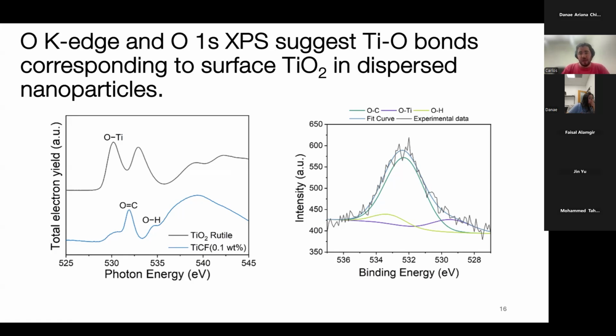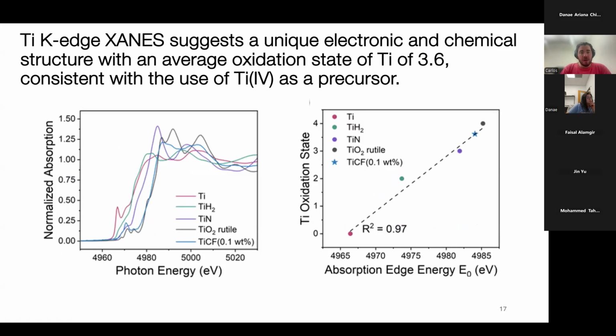We hypothesized that these Ti-O bonds aren't really in the single atom architecture. They come from the surface oxide of titanium nanoparticles that are somewhat forming in our catalyst. So we have some titanium being clustered when we make these catalysts. That's why we don't really call this catalyst a titanium single atom catalyst, and we tend to call it titanium doped carbon nanoflowers, because it is in some way a matrix of both single atom sites with nanoparticles dispersed in the catalyst.